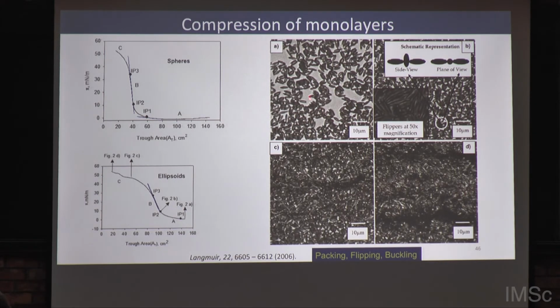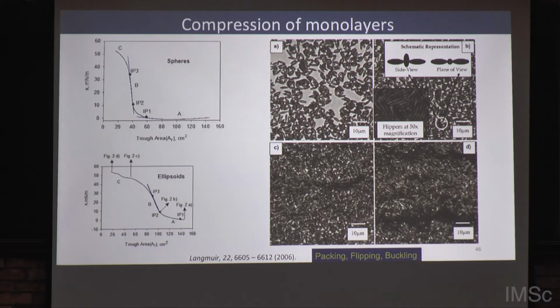right. If you look at this image, this is very different from the spherical picture that I drew. That's because these particles are non-spherical, there are these shape dependent interactions which lead to aggregation of particles. We really don't start with a gas like state. Even if you put in a few particles, they would aggregate and form clusters. Therefore I really don't have a gas like state that you saw for the case of spherical particles, and we see a lot of cases of this side arrangement that you talked about here, Rajesh, where they line up and form these stacks.